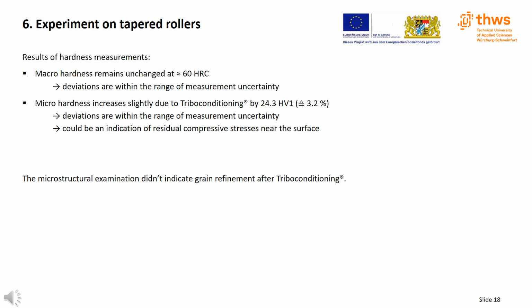Triboconditioning slightly increased the micro hardness. This is an increase of 24.3 HV1, which corresponds to a relative increase of 3.2%. Although this deviation is also within the range of measurement uncertainty, the difference could be an indication of increased residual compressive stresses near the surface. But in order to make a reliable statement, the residual compressive stresses would have to be investigated separately.